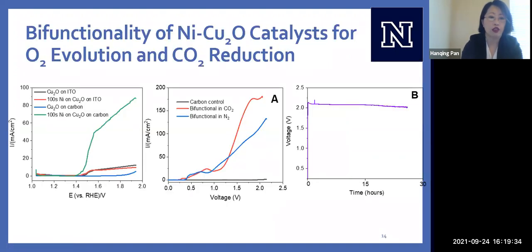So after looking at the CO2 reduction reaction, we want to look at the other side of our reaction, the anode, which is the oxygen evolution reaction. A couple of years ago, a student in our group used this copper oxide and nickel catalyst and tested it for oxygen evolution reaction, but she tested it on top of tin-doped indium oxide. It worked well, but tin-doped indium oxide is unstable, especially under reductive conditions. So I put this catalyst on top of our carbon paper to see if we can do any better, and it actually performs so much better.